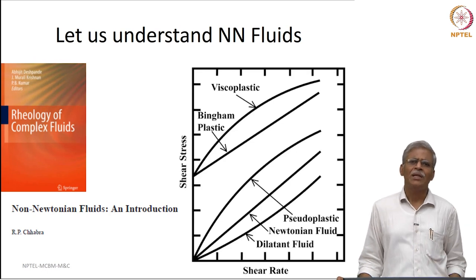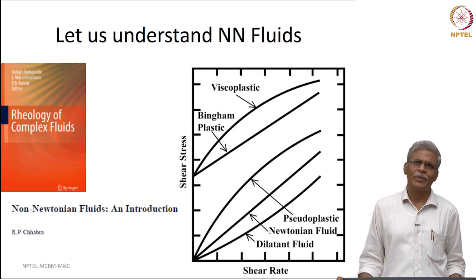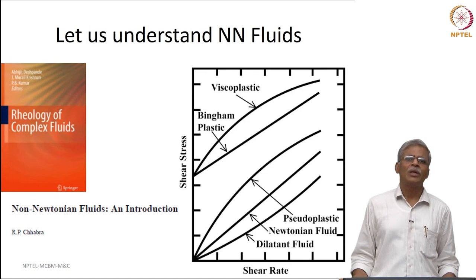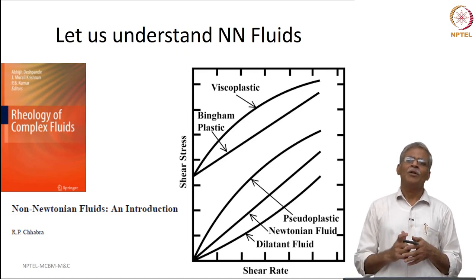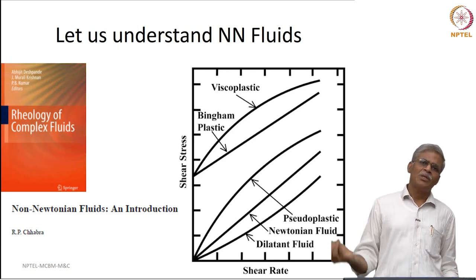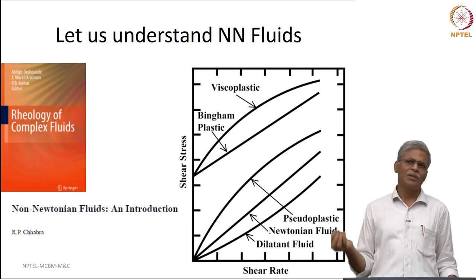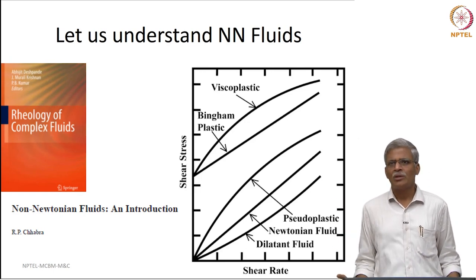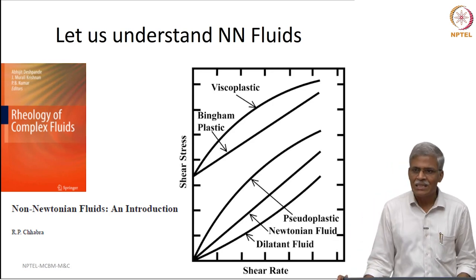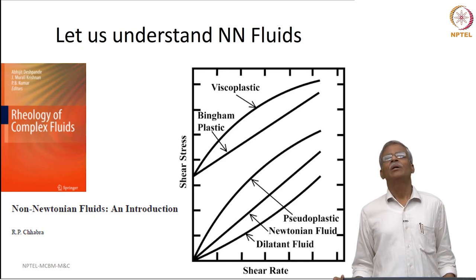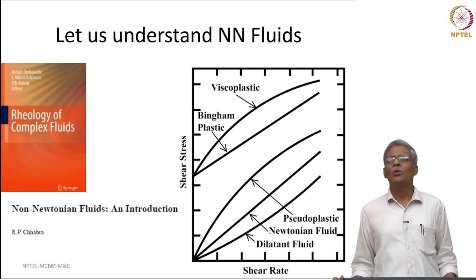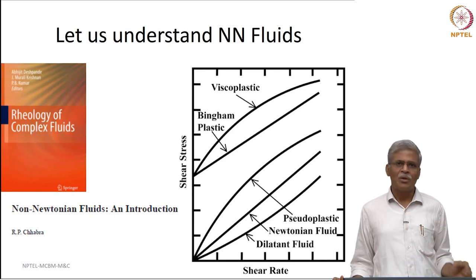Till recently, up to 20-30 years back, there was no issue, basically because most of the bituminous pavements were actually using only unmodified bitumen. And for unmodified bitumen, based on rich work experience, we were able to prescribe some mixing temperature and compaction temperature based on Newtonian viscosities. But in the last 20-30 years, when a substantial amount of pavements are being constructed with modified bitumen, it is found that finding the mixing temperature becomes a non-trivial task.